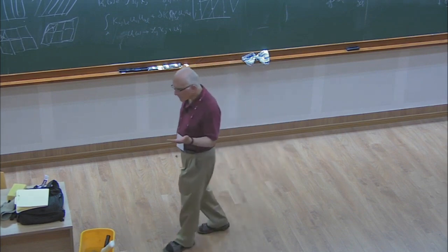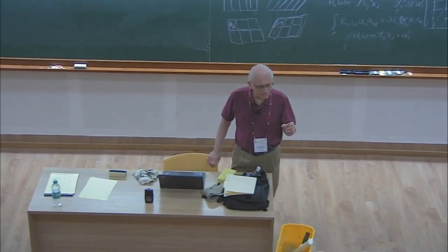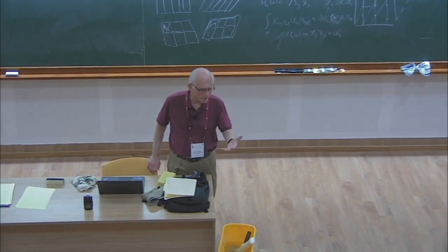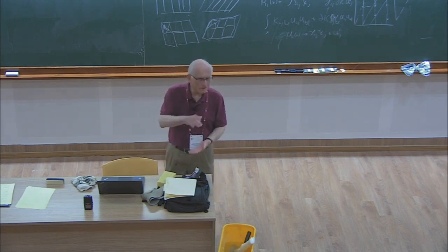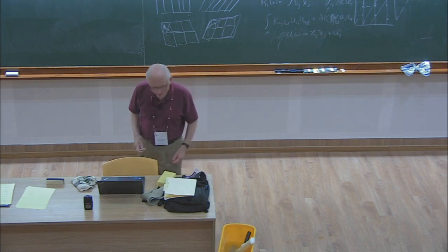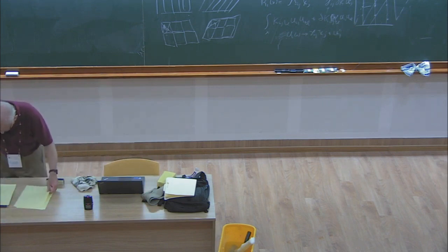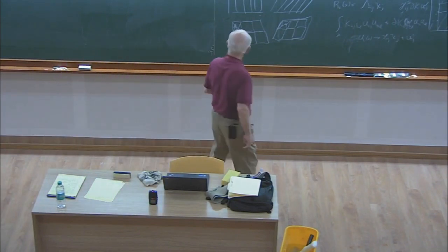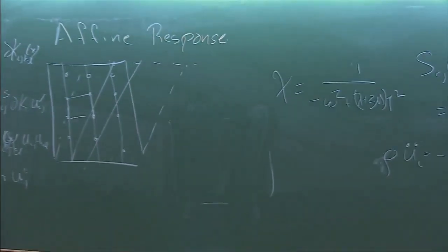So there, what usually happens is that the correlation lengths associated with the non-affine centers are pretty short. And so, if you take a piece of steel, which is not a very regular system, it has grain boundaries and all that all over the place, there's still a well-characterized, essentially isotropic elasticity that goes with it. So it's not a disaster unless we have more complicated situations. Okay, so we've done continuum. We're now going to switch to looking at lattice models.